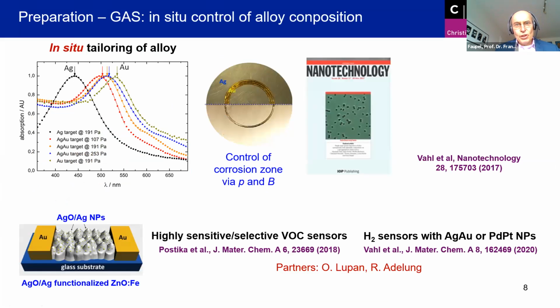Yeah, as I said, not only monitoring is important, you also need control. And one way to get in situ control is to use composite targets. So here, for instance, we have an alloy. In order to produce silver-gold alloys, we use, for instance, a silver target, and here we have a ring of gold within the target, and then we vary the region of the erosion zone, and this can be done, for instance, by varying the pressure. Recently, we also have an approach where we vary the location of the magnetic field, and then we can in situ determine the ratio of sputtered silver to gold, and this allows us in situ to produce different alloy compositions. We can also, during the deposition process, change the alloy concentration, prepare gradients, etc.